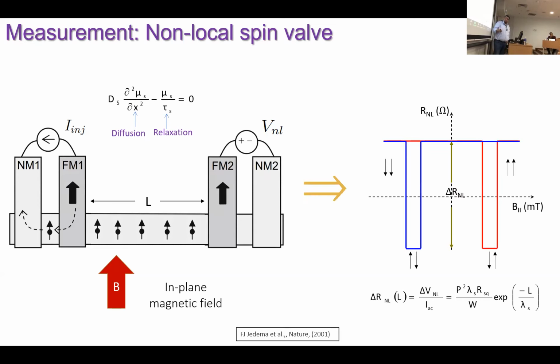And what we do is apply a magnetic field in plane along the easy axis of the ferromagnet, so that these injector and detector electrodes are parallel or anti-parallel to each other. If they are parallel, you have one resistance state, and if they are anti-parallel, the resistance changes, it switches. So you have this rectangular shape, which is proof that you have pure spin current propagation in this material. You can get this delta R, and you know the L. By varying delta R as a function of L, you can get information about the spin relaxation length in this material. So this is one way.